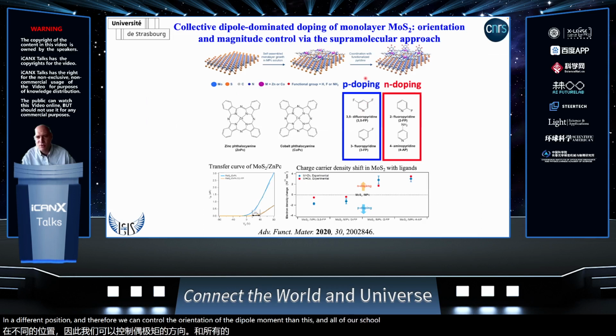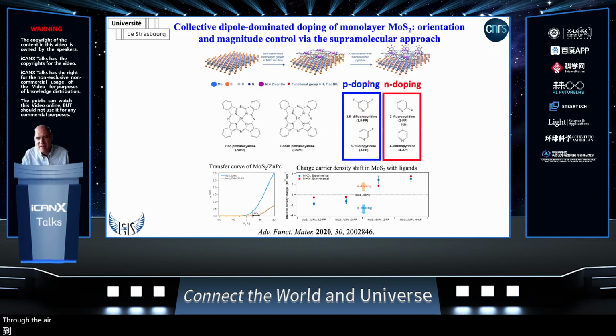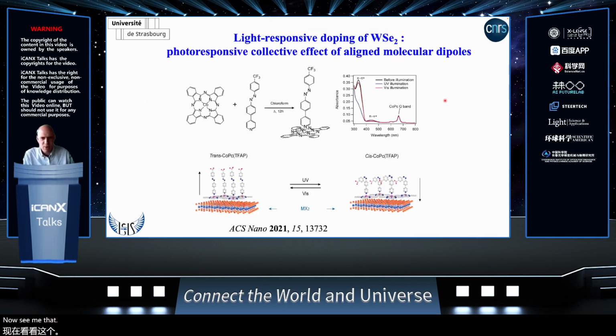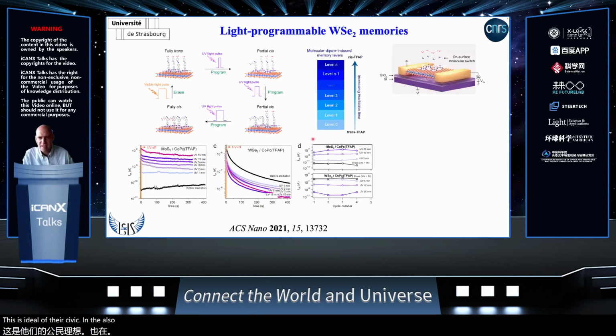This allows us to change from an n-doping effect when the fluorine atom is more or less out of plane to p-doping, and n-doping again when it goes back to the plane. This is the case when we have the fluorine atom in the ortho position, or if we use a nitrogen unit. Now, a similar approach can be done using a slightly more sophisticated molecule, again with a pyridine unit, but holding a pillar that is an azobenzene one. Therefore, in situ, we can change the state of the azobenzene upon isomerization from perpendicular to bent. This is highly reversible, can also be done using pulses of different duration, thereby controlling the population of azobenzene molecules that undergo isomerization. And this allows us to electrically access different levels for multi-level memory application.